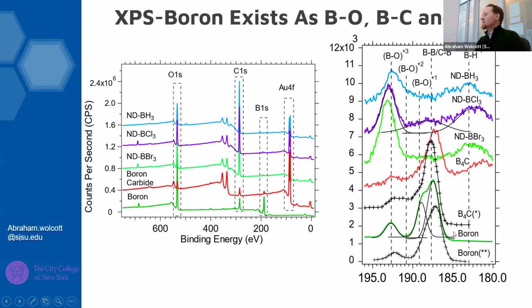If we zoom in on the right-hand side, this is where we would see elemental boron, a powder. This is boron carbide, and then this is the structure of our BBr3, BCl3, and BH3 treated sample. You'll notice that boron is right here at about 188 eV. And then as you get to oxides, you move to the left to about 193. We see some information at about 182, but I think that's more controversial. Some folks have said it's a B-H, but you shouldn't trust it. Most of the relevant information should be between 188 and 193 eV.